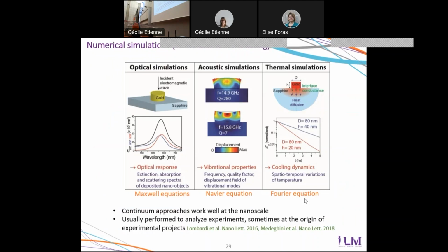So this is done by numerical resolution of another equation, which is the Navier equation. And we also use similar tools for modeling the thermal dynamics of nanoparticles. Here we numerically solve a Fourier equation, and so, starting from an initially heated nanoparticle and an initially non-heated environment, we can see at subsequent instants what the temperature field is in the particle and in the environment. So it's typically something we do after the experiments to better understand what we have measured.